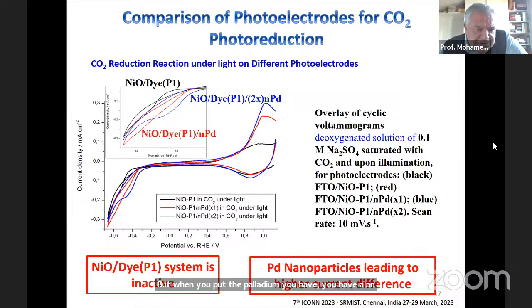But when you put the palladium, you have an increase of the current, which starts as early as -0.4 or -0.2. But it starts before, as I told you, it starts here, but you can see it better here. And when you enhance the amount of palladium, as you can see, there is this wave which appears clearly. This is the proof of concept that we have a real effect of the dye on the palladium. When the dye is negatively charged, the palladium can get photoreduction of CO2 easily, and it starts much earlier. This is the photoelectrode we did.